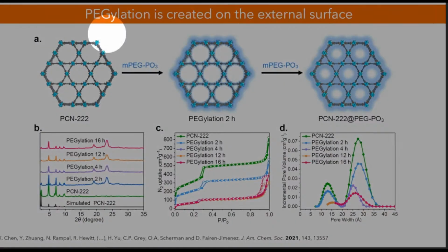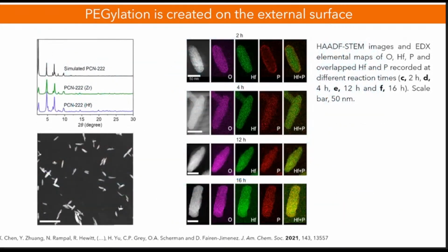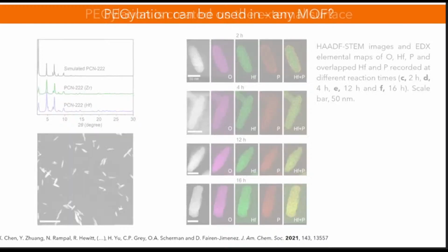This is basically the idea. We are going to have our structure, we are going to be able to load this with different drugs, and we just basically pegylate the material. If we pegylate this for too long, we can see that the PEG is able to enter inside the porosity, which is something we want to avoid. But mostly, when we do this in only 2 hours, we can protect just the external surface without damaging the porosity of the materials. This is how the materials look under the microscope, and basically it's telling us that in 2 hours, this is the nanoparticle, this is the oxygen and hafnium, which is equivalent to zirconium, and we can see that the phosphorus from the phosphate groups and the PEG is concentrated mostly on the external surface of the material. And as soon as we increase the time, we can see that the PEG has been attacking the center of the material, and it's not only on the external surface. So basically this means we need to stop here at 2 hours.